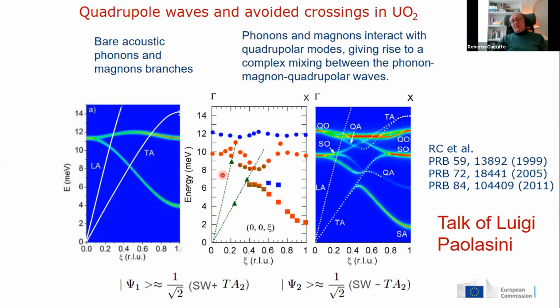Instead, neutron experiments show a much more complicated pattern. This is because of the strong magneto-vibrational interaction and electric quadrupole vibrational interaction. These interactions, and the presence of a strong contribution to the superexchange field of multipolar origin, in particular quadrupolar superexchange coupling, produce at least 2 or 3 strong avoided crossing points, with the formation of mixed spin phonon modes, mixed spin quadrupolar modes, and mixed quadrupolar phonon modes.